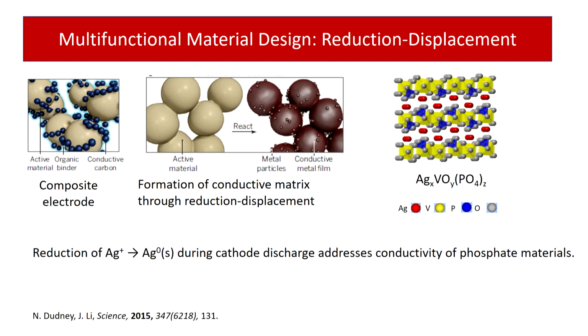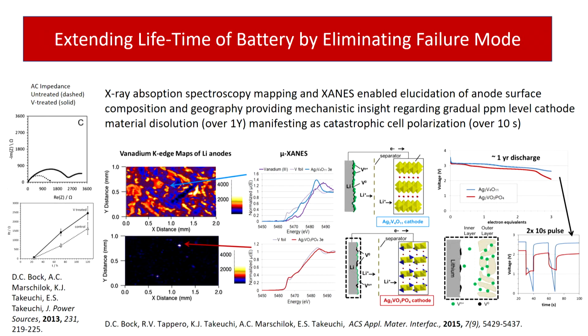The example I want to show you is silver vanadium phosphorus oxide. Phosphates typically are not conductive. They're pretty resistive. The idea was by including a silver cation, reduction of that silver cation, silver metal, should overcome some of that resistance. This material is also important because the solubility we were able to demonstrate is much less than the oxide. Silver vanadium oxide is an important commercial battery. It's used for implantable cardiac defibrillators. And in fact, vanadium dissolution is one of the life-limiting features of that active material. And by going to the phosphate, we can minimize dissolution.